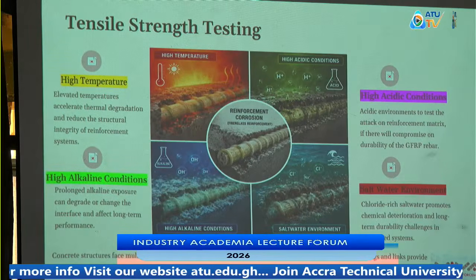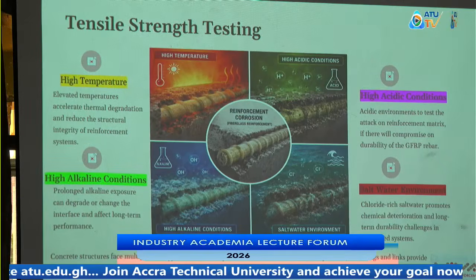And for high temperatures, I picked 240 degrees Celsius. And why 240 degrees Celsius, if you ask? Because this is the temperature at which the concrete cover is compromised and the cracking becomes visible. And at this stage, the fire is already reaching the reinforcement inside.